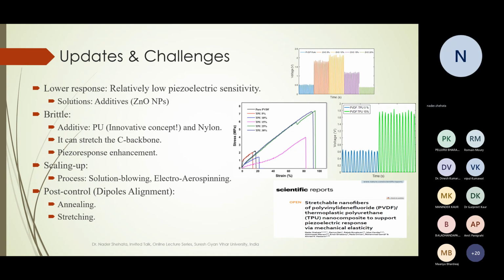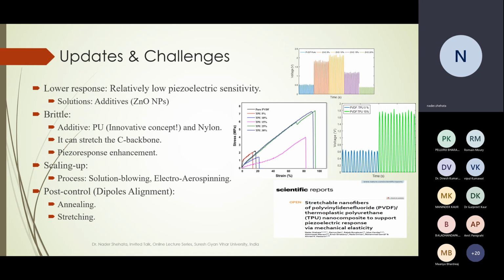So in this case, we have to think about some additives, for example, like polyurethane or nylon, so that you can increase the stretching capability or increase the breaking point of the strain. However, as you know, here we will have a trade-off. You are adding another additive, so you are expecting that you are losing some of the main material, PVDF, and that you will have a lower piezo response.